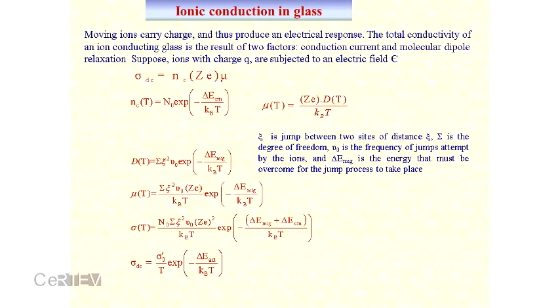I have already expressed the conductivity in terms of the charge carrier concentration, the charge, and the mobility, because the charge is different for different alkali ions. If we assume that the charge carriers are Arrhenius with some activation energy, the so-called creation energy, and the mobility also has the same type of behavior, with the migration energy, then ultimately we can express the conductivity as a function of sigma 0 by T and an exponential of activation energy by kT. And this is the theoretical value.